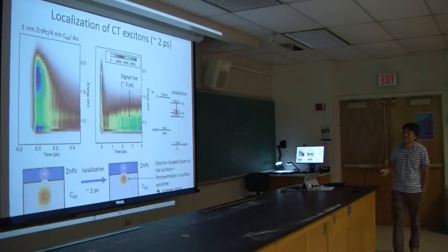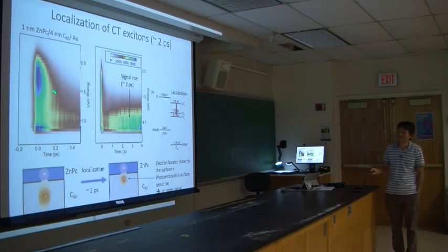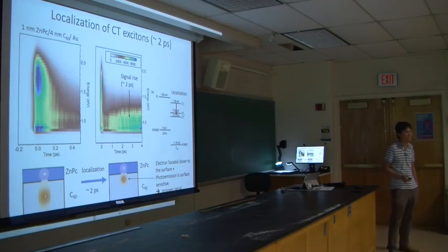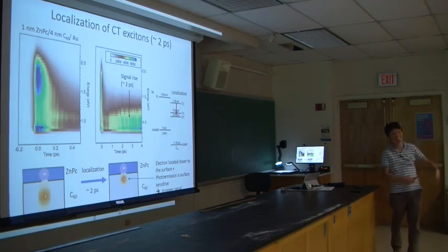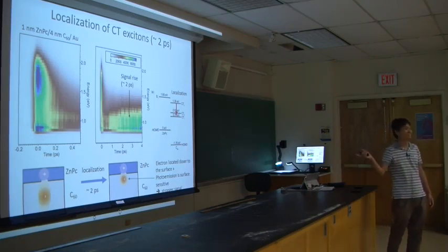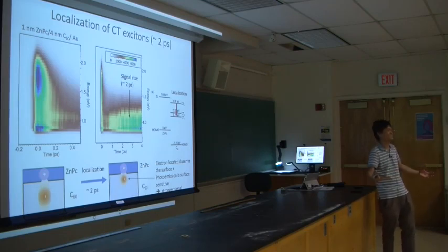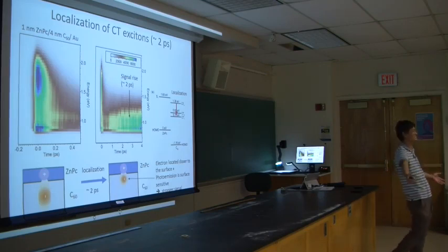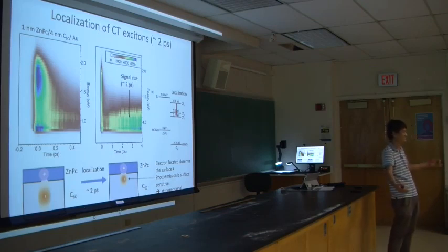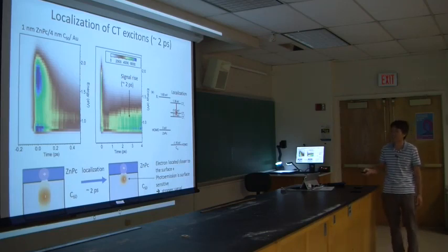What's interesting about this experiment is you see this charge transfer signal disappear in about 100 femtoseconds. And then at a later time, about a few picoseconds, we see this signal rise in this lower energy CT state, right? So what happened? Usually what we expect is you see one decay and the other rise, right? But in that case, it seemed that the electron disappeared between that 100 femtoseconds and that few picosecond time scale. It disappeared from our probe, and then later it comes back up, right? So you see that fast decay here, and then later the signal rises, right?